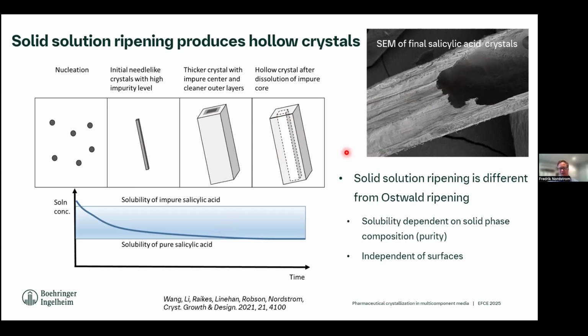So this solid solution ripening, or this solid solution effect, is quite known in inorganic, but not so much in organic again. And yeah, it's obviously very different from what we call Ostwald ripening, right? So here we have a solubility that's dependent on the composition of the solid phase. It's not a surface area or size, like a nanometer size effect that's coming from this capillary effect that's in the Gibbs-Thomson equation and so on. So it's independent of surfaces, but it's directly dependent on the solid phase composition.